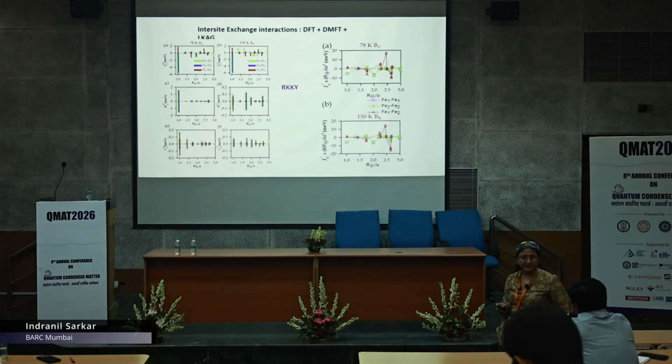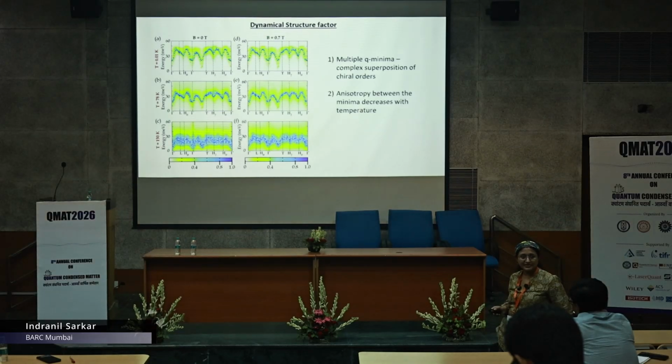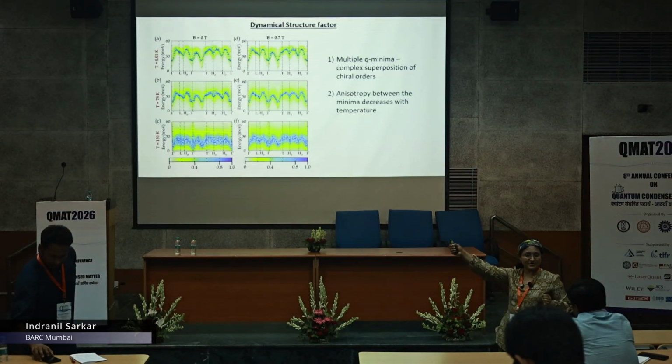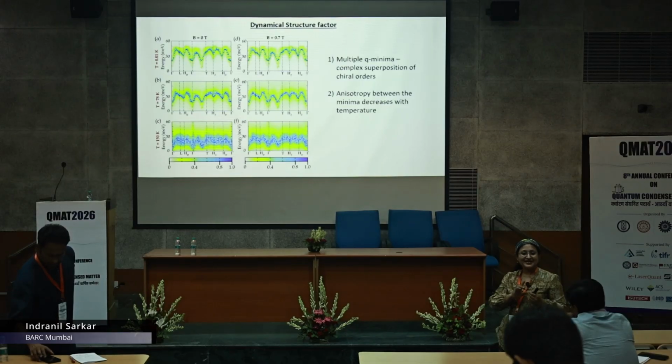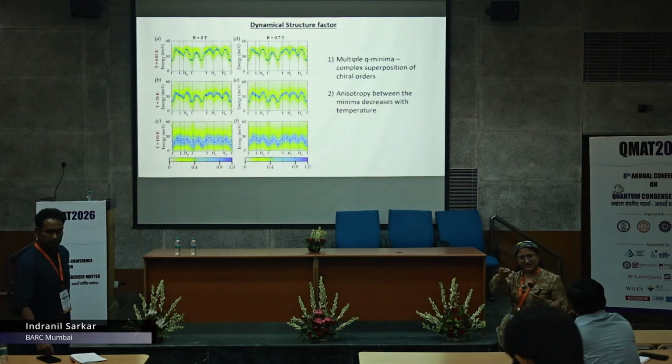This is a long range interaction, definitely, because if you look at the spin correlation, you get a magnon spectra which is surviving up to 150 Kelvin. So the magnon is surviving up to 150 Kelvin, so it is a long range interaction. The very ordered spirals are present below 50 Kelvin only. After 50 Kelvin, the spirals become very long range. So almost collinear, not collinear I would say, but these are in-plane spirals only.